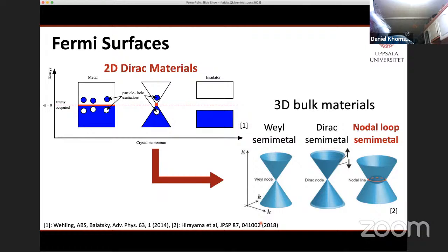That's actually a situation when you have two overlapping bands, and you have a Fermi surface. In one band, you have a certain number of electrons, and in another band, you have an equal number of holes. That's actually an electron and hole Fermi surface, two bands, conduction band and valence band. With coinciding Fermi surfaces, this situation is known to be absolutely unstable with respect to what people call an excitonic insulator, with equal numbers of electrons and holes.